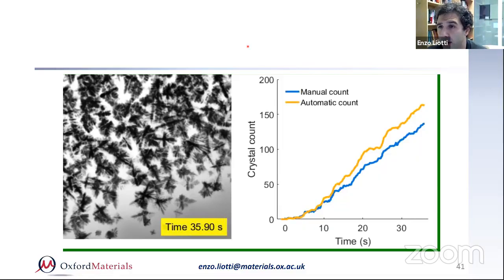So it's literally like a plastic bag when it shrinks, right? Because we are looking through the sample plane, that doesn't really matter for our type of imaging. So we were looking at a sample of more or less 25 by 15 millimeter in size, 200 micron thick. But the area we were imaging was normally 2 by 2 millimeter in the center.